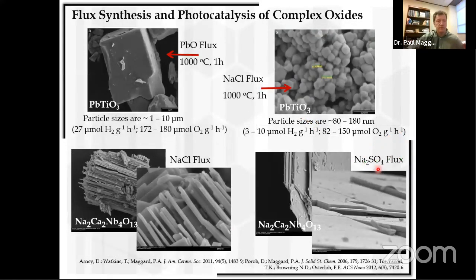Just a few more examples from flux synthesis approach here. One is lead titanate, which has a relatively high dielectric constant. You can make it in a lead oxide flux, and you can have very large cubic shaped particles. And as well, if you use a sodium chloride flux, you can make much smaller particles, more in the nanometer size scale. And if you compare the activities for oxygen evolution and for hydrogen evolution, surprisingly, the much larger particles